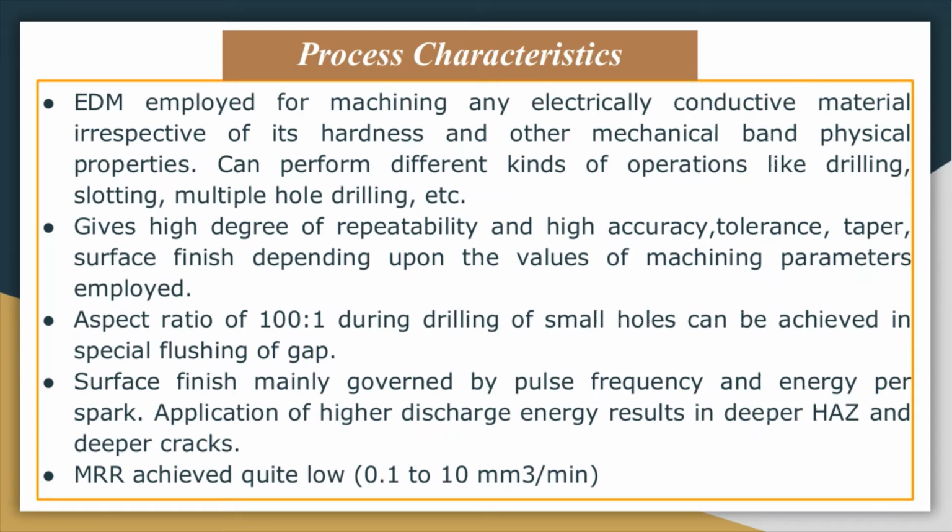Surface finish is mainly governed by the pulse frequency and energy per spark. So if we increase the energy per spark, your material removal rate will increase. If we reduce the frequency of current, then also your material removal rate will increase. But if we increase the frequency of current, your material removal rate will decrease, your surface finish will improve. So surface finish is mainly governed by the pulse frequency and energy per spark. Okay, and application of higher discharge results in deeper heat affected zone and deeper cracks.